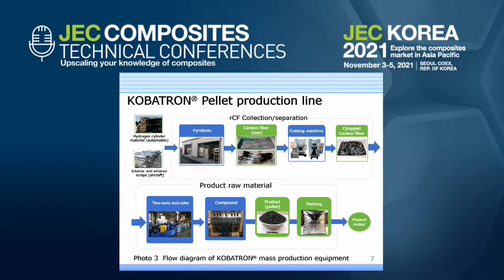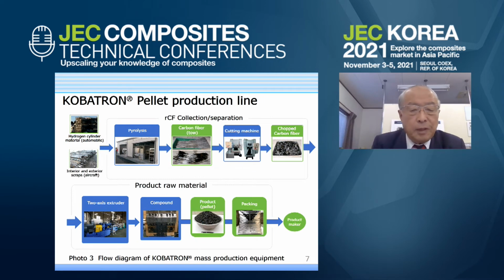And the backside is a very secret area, and we can recycle the gas from heating, and also the evolved gas is returned to the furnace with a small amount of air. And the obtained material next has a very shiny surface, as you can see. This shiny surface means we can get very good condition carbon fiber, no oxidation. If residual material is on the surface, it is very dark and not shiny, but we get a very shiny surface every time.